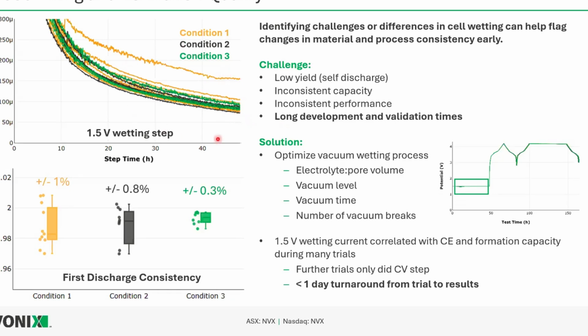We found very quickly that this wetting step, measuring the current very accurately through this step to microamps levels, and of course these are accurate to nanoamps on the UHPC, the consistency here correlated very well with the first discharge capacity and the consistency of cycling down the road. And so we were able to take something that could take weeks or months of cycling a cell to figure out if there's going to be some plating in it or leading to differences in fade, and turn this into less than a day of turnaround from trial to results and iterating on the next step.